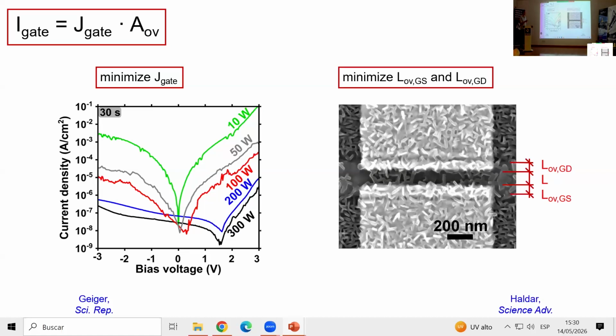And the other parameter then here again is the overlap area, and we're minimizing that by minimizing the distance by which the source and the drain contacts, those are the white regions here, overlap with the gate electrode, which is a little bit difficult to see because it's buried underneath the organic semiconductor here, but you can maybe see it here. So the overlap lengths are these LOVGS and LOVGD values here. And so we're making these as small as possible. So in this case, they're about 100 nanometers.